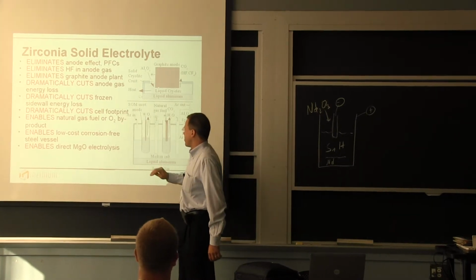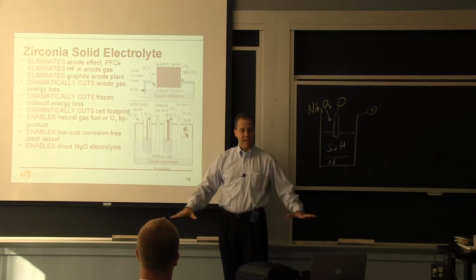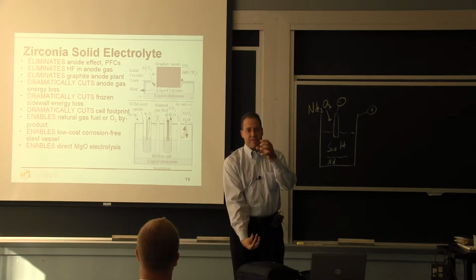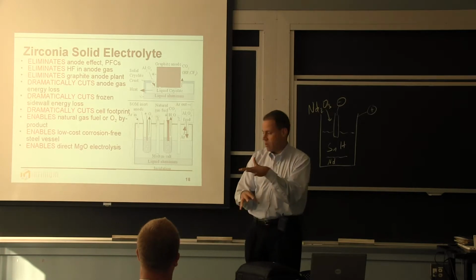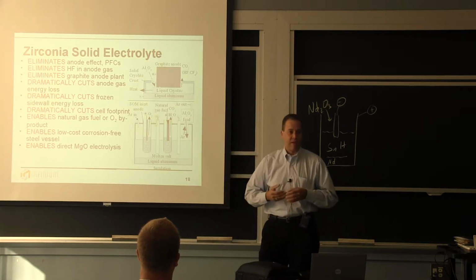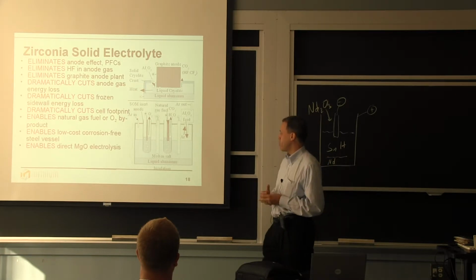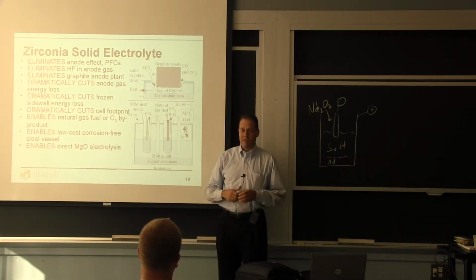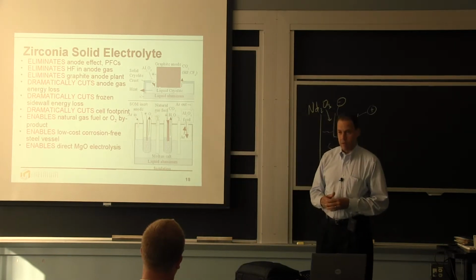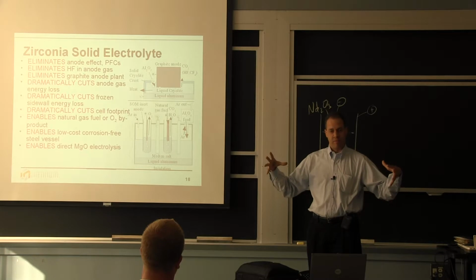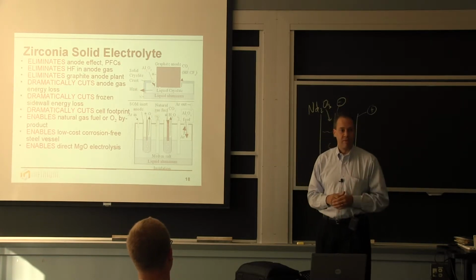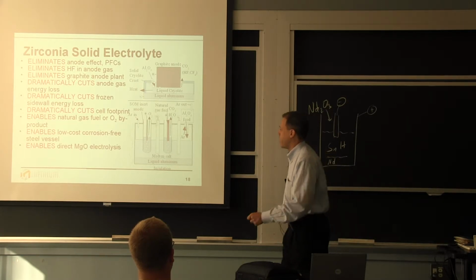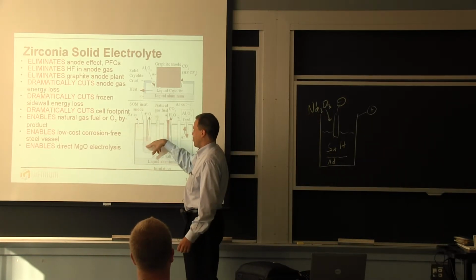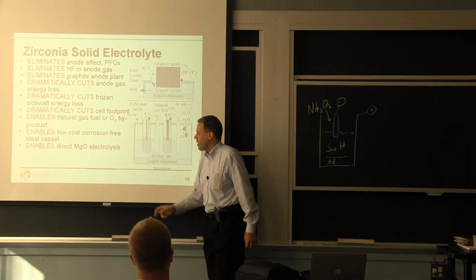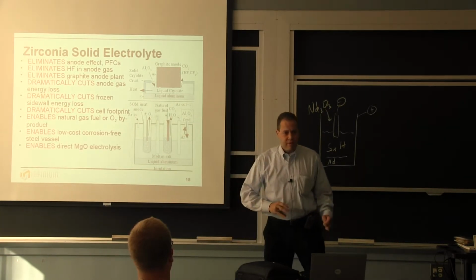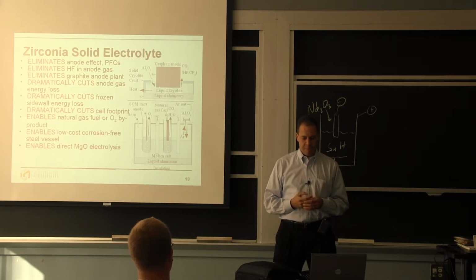It also cuts the cell footprint, because now instead of a flat anode and a flat cathode, you can go into the third dimension. You can have these zirconia tubes extending deep into the molten salt and the cathodes as well. And there's some limit to that. We can get between 3 and 10 times the productivity per unit cross-section area versus the Hall cell. So your overall footprint of the plant can be about half, we think, of the footprint of a traditional aluminum plant. Furthermore, as I mentioned, you can produce an oxygen byproduct or use natural gas fuel, steel vessel, and this also enables direct electrolysis of magnesium oxide.